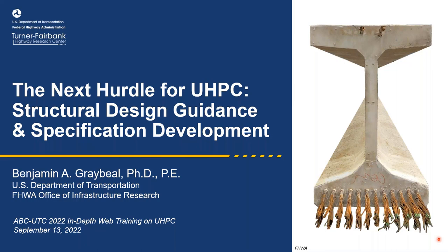Ooh, I think we're combining two things there. When we do the tension tests, as we get to localization, different cracks will sort of connect together. But you need to look at when that localization behavior first begins to happen. We've run full-scale shear tests, and what we see is a lot of parallel, very tightly spaced cracks that align with the theta angle for shear, for beam shear. And that is the angle where you do your capacity calculation.